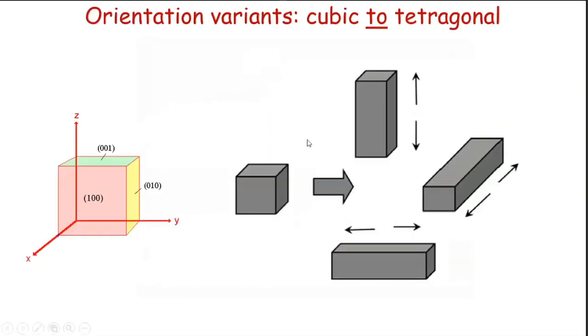One thing more I have to mention before I show you the microstructure is I'll use this word orientation variant, and therefore I brought in this slide. So if you start with only a tetragonal transformation, that means I'm essentially only going to stretch the C axis. So we take this basis, and let's say this is the original basis to which we'll refer all this transformation. We start with this cube, and if we stretch it along the Z, we get this variant. If we stretch it along the X, we get this orientation. And if we stretch it along the Y, in relative terms, we get this variant. So you have 3 orientational variants which have got different orientations with respect to each other. Now, in the normal case, if you take the martensite, where we have taken a very specific case of a tetragonal transformation, but in the general case, we have about 24 orientation variants that result.